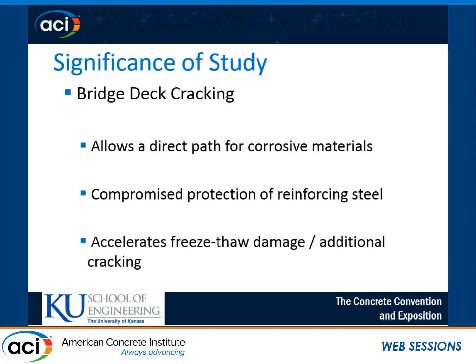So, significance of bridge deck cracking. If we're going to repair or replace all affected bridge decks within our infrastructure system, that's going to be billions of dollars, and this accounts for hundreds of millions of traffic trips across the affected structures annually, so that's quite a problem we're facing here. The main issue with cracking, especially settlement cracking, is that when you have cracks developing directly over reinforcing steel, that's a direct path for de-icing salts and other corrosive chemicals to quickly penetrate down to that steel, and you have earlier initiation of corrosion and accelerated corrosion rates, which will even further deteriorate your structures.